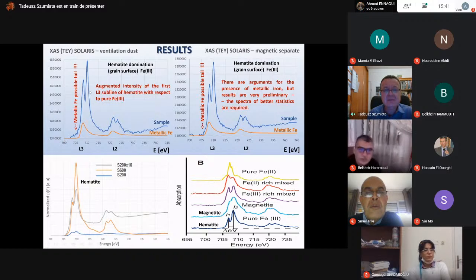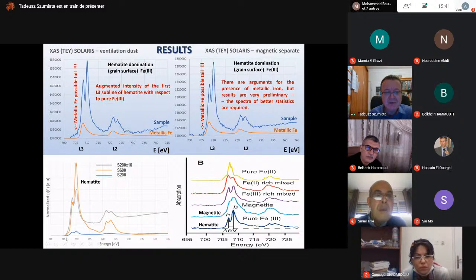So in this spectra, we can see the dominating structure of the hematite, but as you can see on the reference spectrum, the absorption should start above 705 electron volts. Our experimental curve starts earlier. And here you can see the spectrum for the crude sample and here for the magnetic separate. And even here you can see that this part of the spectra is similar to the reference spectrum of metallic